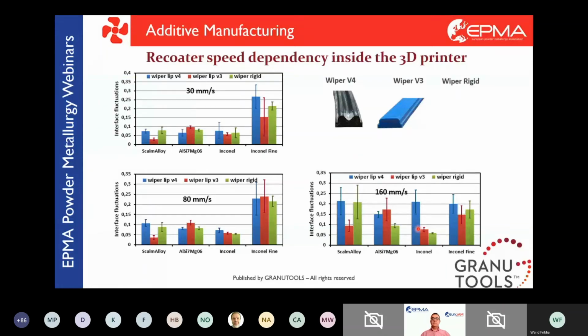But inside the GranuDrum, there is no way. The GranuDrum is just there to do powder characterization. So if you want to take the powder shape into account, the only way was to build a test bench with the wiper on it and spread the powder, which is a very complicated method that requires a lot of room, a lot of time, and is not as easy as the rotating drum principle, where you just pour powder inside the rotating drum, wait 15 minutes, and get all the results.